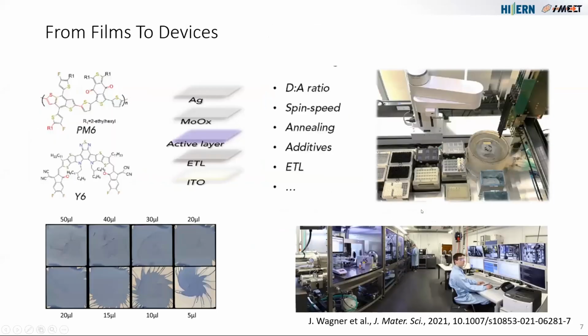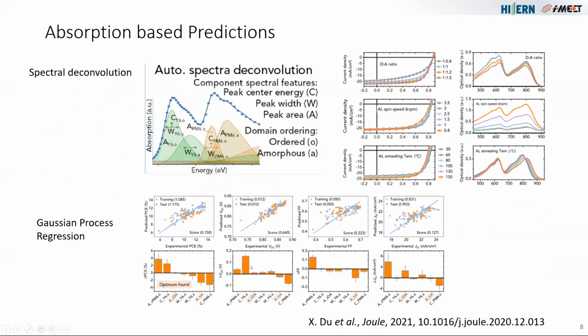From there on, we basically started to look at the cells that were made with the robot-based platform, where here Jared has been developing a lot of the components. You can see here the automated spin coater that is being operated with pipetting channels. And since we have very precise control of where the drop is going to hit the cell, we can actually make fully functioning cells with only 15 microliter of solution, or 20, somewhere in that range, which is very nice since we don't need a lot of materials for making these devices, which then allowed us to make a lot of them,